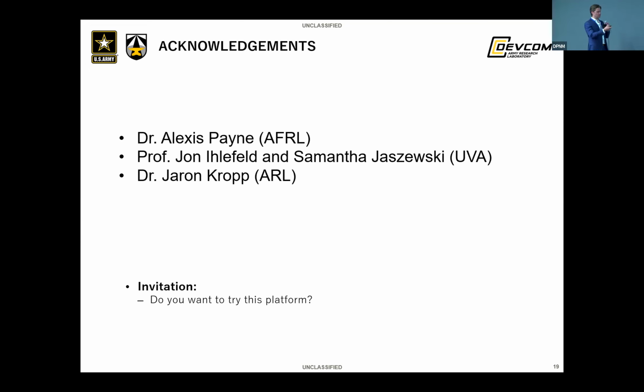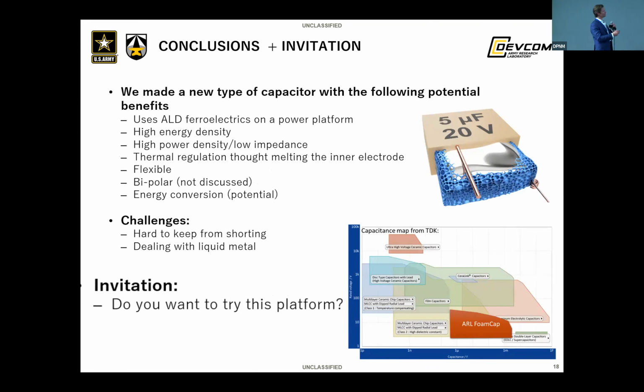If you imagine the original configuration, and let's say this whole thing's coated and you just have one cable that's threaded coming here, and this is coated with ALD and coated with platinum. If you etch back the platinum this much and etch back the ALD this much, then you have two points on this wire, which are the top and bottom electrodes. It just seems scary and hard to try to accomplish that. And there wasn't an etch chemistry that made it sound like a knockout solution, but you certainly could complete this by doing a top ALD coating as well, which maybe you'd like to try.